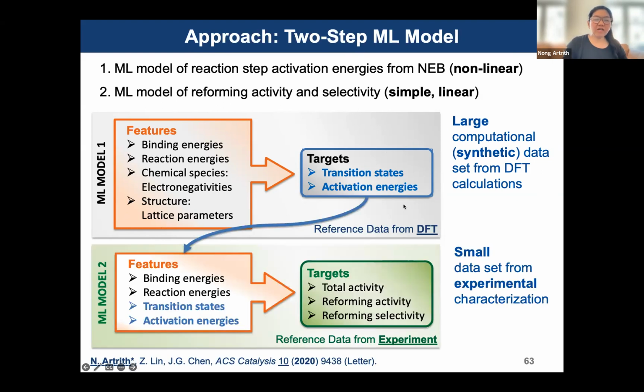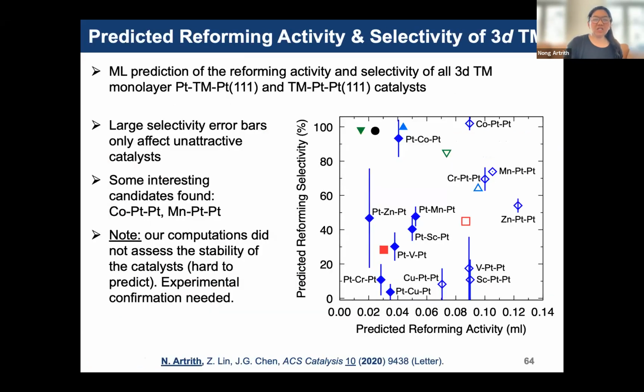And then we learn and get the information and use the linear models, and also get the information from the predictions that we get from the DFT. And then we predict the total activities, the reforming activity and the reforming selectivities, as a combination between the DFT information and the experimental measurements. This is the prediction that we have. So far, again, we're only looking at the 3D transition metals, only the 3Ds in the periodic table. On the right-hand side, as you can see, the x-axis is the predicted reforming activities, and also the predicted reforming selectivity. And this is the best known already from the experimental measurement that they also show.